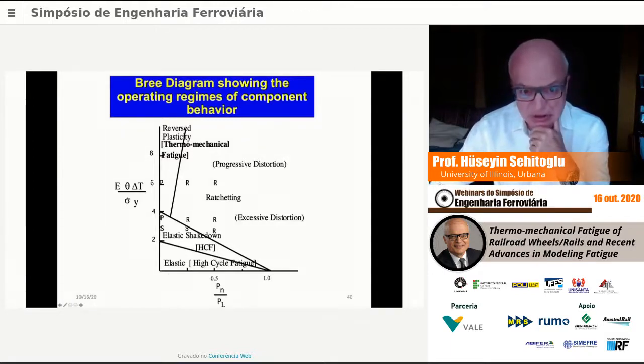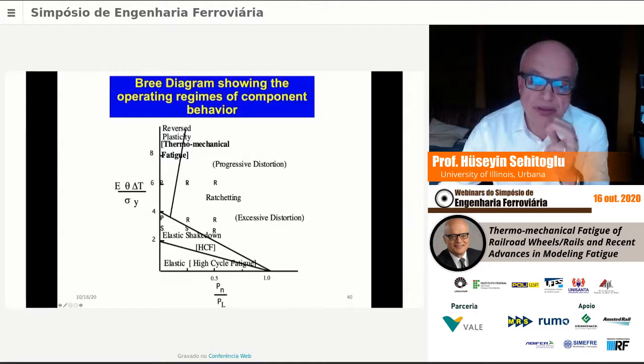Thermomechanical fatigue occurs in a very specific case. It's the case of reverse plasticity. And there the net section loads are not necessarily very high, but thermal loads are quite high. So with that two-bar structure, we conducted experiments a long time ago to observe, under the combination of this load and this delta T, ratcheting.